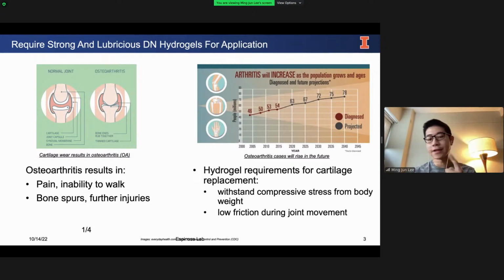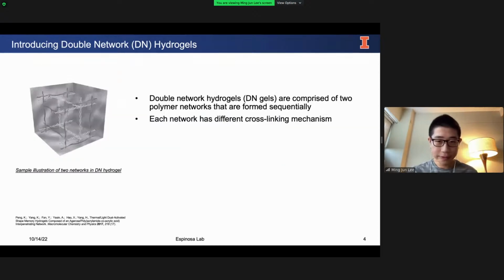The first is that the hydrogel must be mechanically strong enough to withstand the compressive stress from our body weight, as well as having low friction so that you can lubricate the knee bones during joint movement. And that's where double network hydrogels come in. Double network hydrogels are comprised of two polymer networks that are formed sequentially, so one before the other, and they commonly have different cross-linking mechanisms between the first and second network.